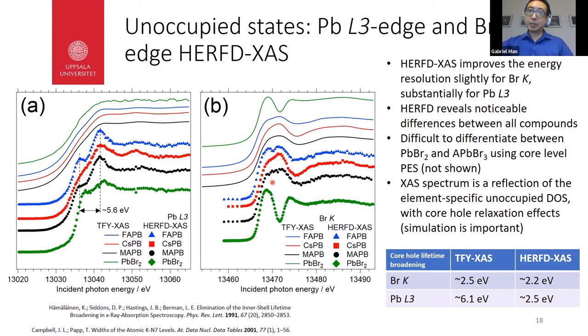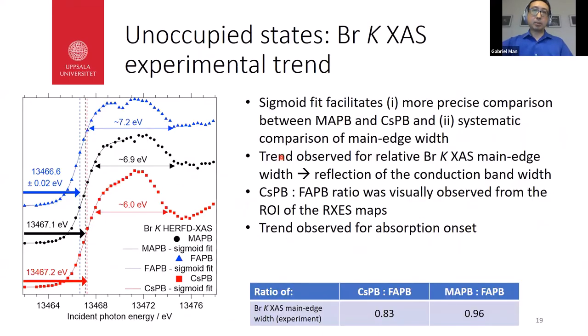Since the XAS spectrum is a reflection of the element-specific unoccupied DOS, albeit with core-hole relaxation effects, in the coming slides I'll show you what we can extract with the help of simulation. But first, we will try to extract some trends from the experimental spectra alone. On the left-hand side is a comparison of the bromine K HERFD XAS spectra for the three perovskite compounds.